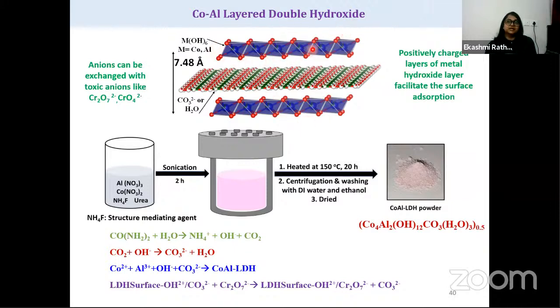Here these layers are positively charged layers of metal hydroxides, and they facilitate surface adsorption. And the anions basically comprise a carbonate layer. This carbonate is non-toxic in nature and can be exchanged with anionic species like dichromate or chromate. So in the lab, we synthesized it using a small pressure cooker, and we used aluminium nitrate and cobalt nitrate for the synthesis, and we formed this pink colored powder.